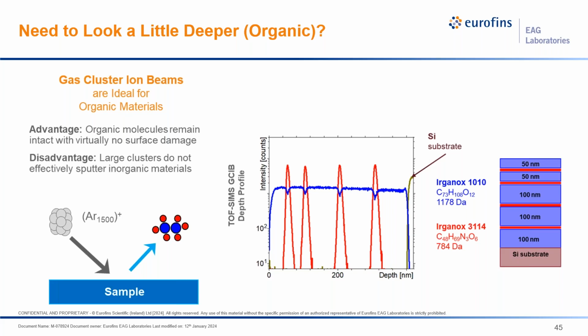great interest. And this is an example using a GCIB to sputter depth profile through a stack of thin organic components. Different Irganox materials, Irganox 1010, Irganox 3114. These are all additives typically used in plastics. So we can see that here. So these 50 nanometer films doing a sputter depth profile and maintaining the organic information as a function of depth.